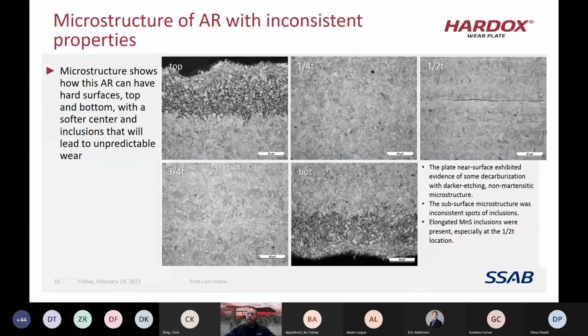So this is basically a micrograph showing a typical AR plate, and what you can see in the top and bottom pictures is that, at the surface of the plate, the grain structure is somewhat different. So whenever you take a hardness measurement on a plate, if you don't grind down far enough through that top layer, then your hardness measurement is not going to directly represent what you see throughout the body of that plate. You can actually have a much different hardness value at the surface of the plate than at the center of the plate.